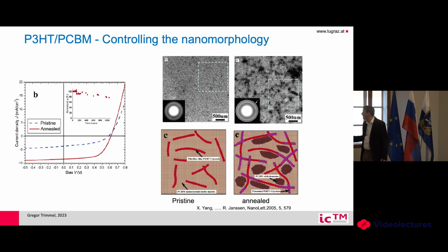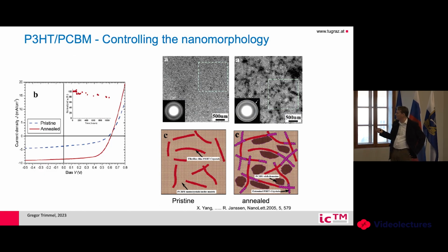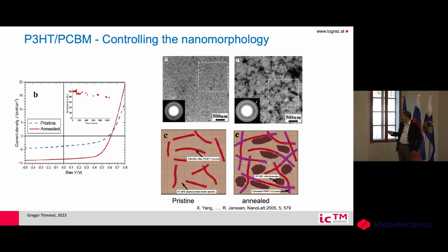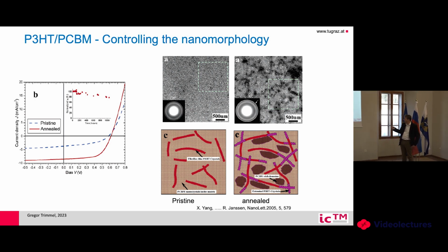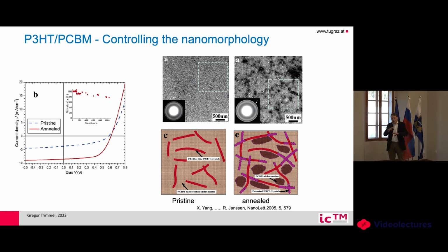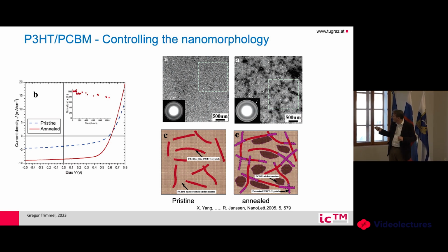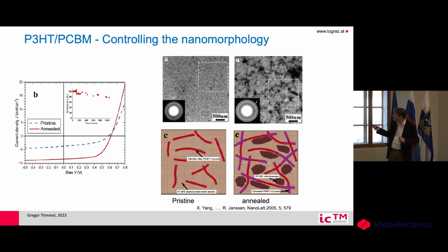This is one of the workhorses for a very long time. This was called P3HT polymer, also with a fullerene derivative. And actually, if you spin coat this, so if you make a coating of these materials together, you see just a grayish surface, because they are really, really intermixed with each other. Yeah? So you see perhaps here a little bit these fibrils, which are coming from the polymer. So this is a sketch of how the scientists thought that it looks like. So you have these polymer fibrils, and then you have a homogeneous mixture of the material. And the solar cell is this blue curve. It's a very bad solar cell, around 2% actually. Yeah?